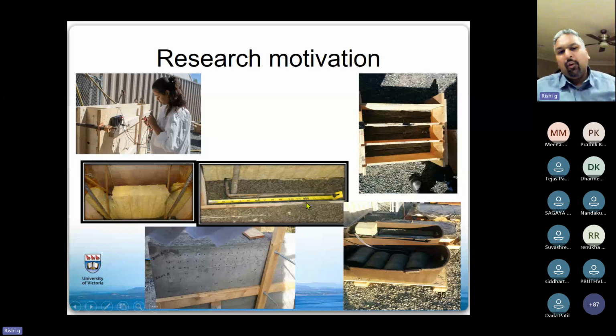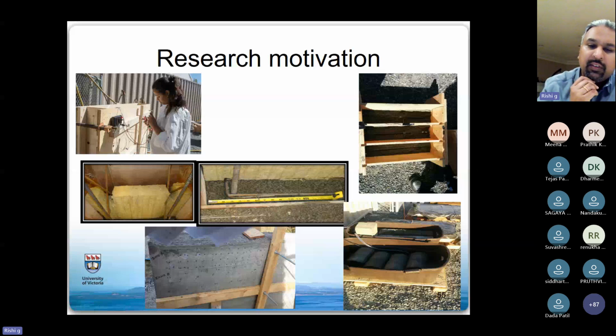Both types of shear reinforcement have their own issues because you have to cut through the insulation to go across. So our structural designer partner was very interested in finding a solution. Here is a top-down photograph. You're trying to find out what the bond of the rebar is when rammed earth is placed across the rebar. Of course, in this situation it would be different. Rammed earth would be going around the rebar, so a different bond. In the bottom right photograph, we were trying to find out the wetting and drying effect. So I have different cycles of wetting and drying. What would happen to the rammed earth's long-term durability? This is a small mock wall that we constructed using rammed earth, and we looked at its long-term deterioration using a non-destructive test method.